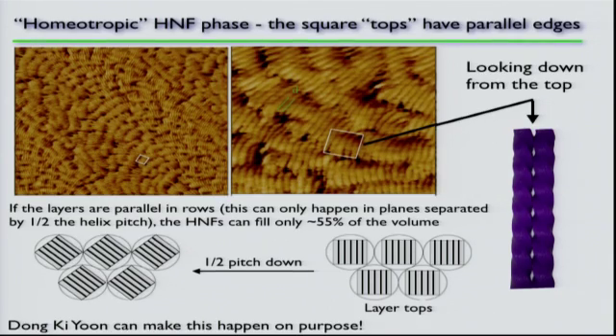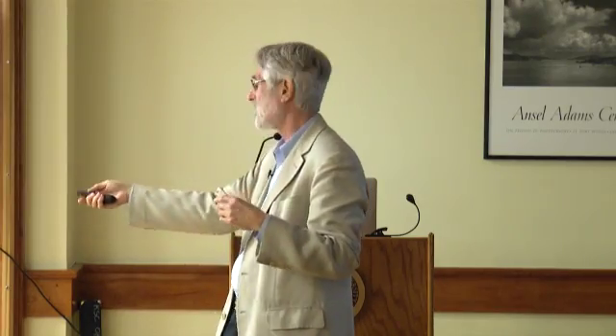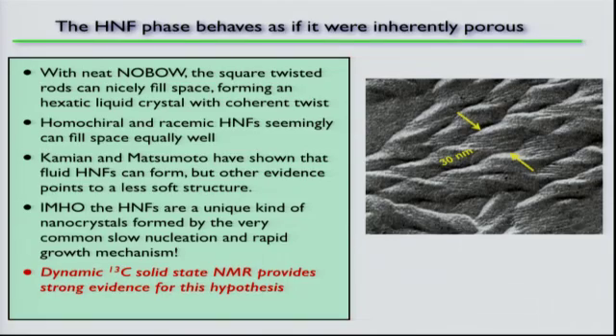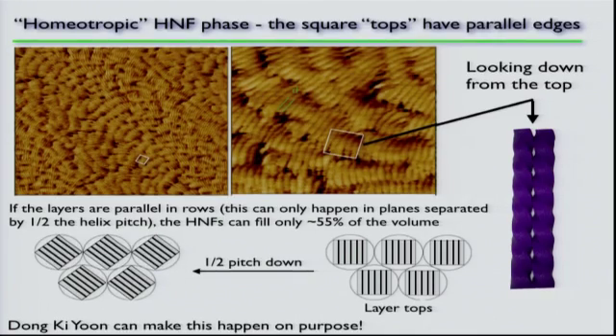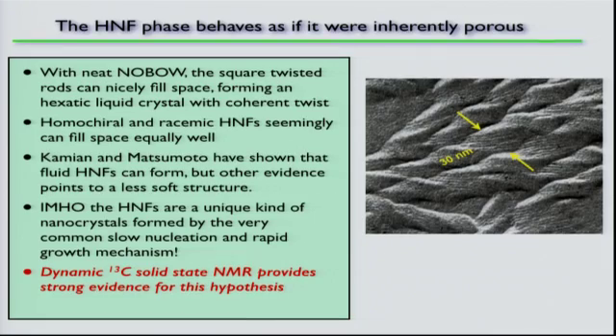And so actually, this is a very porous structure. There are these holes that you can't avoid, and about 45% of the volume is free if the helical nanofilaments are oriented like this. Okay. With the neat material, you can actually nicely fill space by doing a few slight rotations or offsets. I'll show you that. You can get rid of that 45% of free volume. Not here. There's no way to get rid of it here because of the tops of the squares, you're seeing them. There's this plane that has the tops of the squares parallel like that. If you go down, you can't avoid having these holes. But if you allow the things to change in some way, you can fill the space.